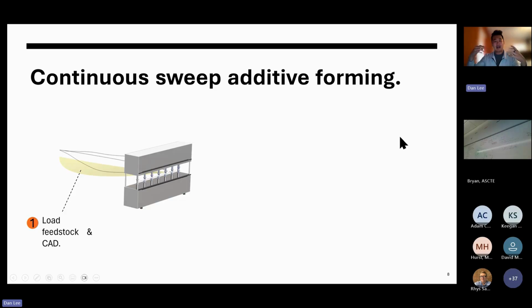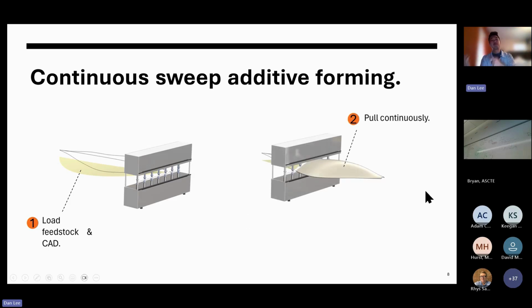So on a very high schematic level, the machine is reduced to, let's say, that frame. In that frame, there are these actuators with a white material, which we use as the adaptable molding surface. We load our fibers, and like pultrusion, we use continuous fibers. We can pull them through a bath, and then we load them into the machine. But like 3D printing, we also load a CAD file, and we have a way to communicate with this machine. As we continue to pull that part through the machine, we can shape it and cure it simultaneously.